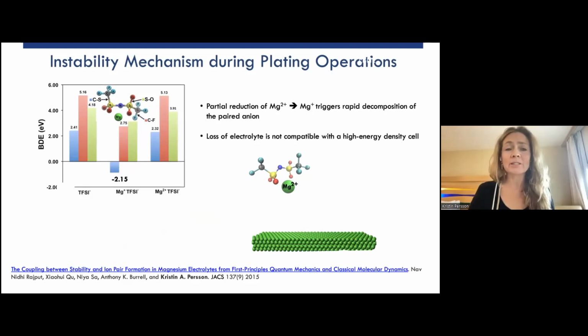So what we did in order to figure out whether TFSI in particular was stable during the sort of idealized plating conditions, first we could calculate whether TFSI by itself is stable. That's sort of a sanity check, because obviously it should be. So we broke the bond. So this is the bond dissociation energy, where we can calculate the bond strength of all the different unique bonds in TFSI. And of course, those are all endothermic, which is very nice. They're stable, it's a stable molecule, stable anion.